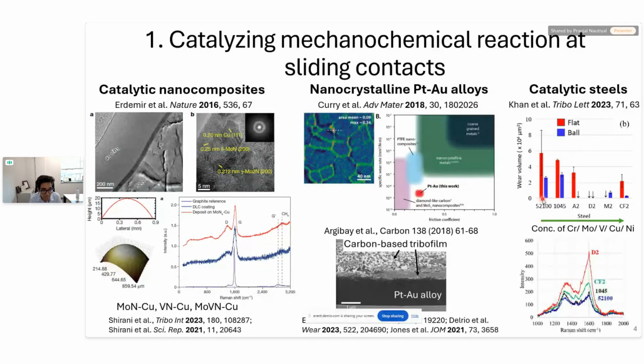And later on, some Raman spectroscopy of the surfaces revealed the formation of a carbon-based film. And the greater the intensity associated with these carbon-based films, the better the wear resistance, as you can see for D2, which is a sample with relatively higher concentrations of chromium. So we can see from these prior studies that the incorporation of catalytic elements could provide an excellent pathway for inducing in situ formation of carbon-based tribofilms at sliding contacts, which then provide excellent wear resistance.